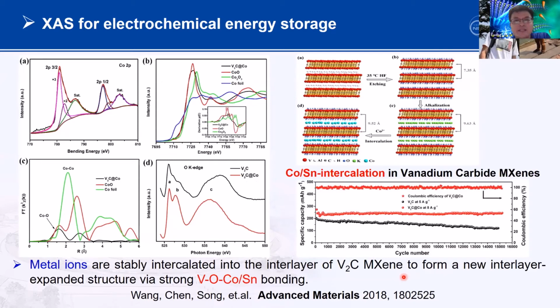We understand that with layered materials you have a really large space at the interface, right? You can put some guest atoms inside the channel, and you can use the functional groups to bond with the guest atoms. So here we try to put metal atoms inside the channel, because for this kind of material, when used for electrodes, the structure is very easy to break, very easy to destroy during the reaction. So if you put atoms here, you want to have some chemical bonding here.